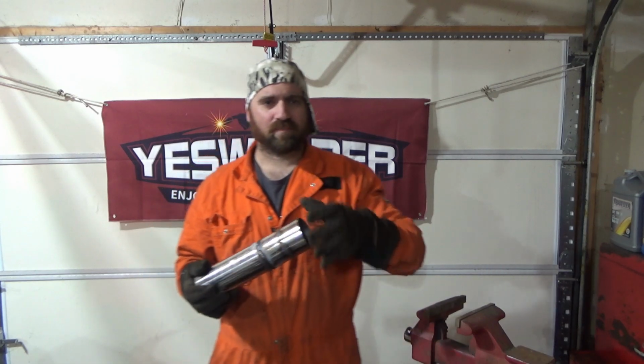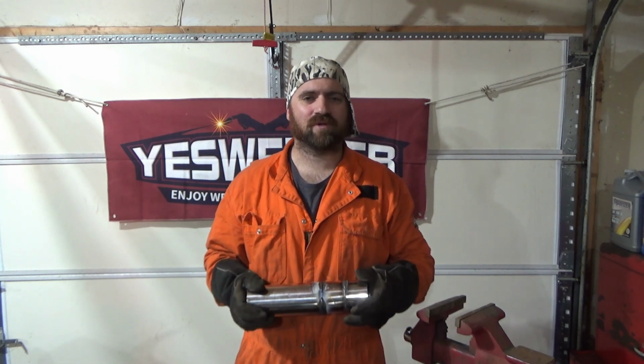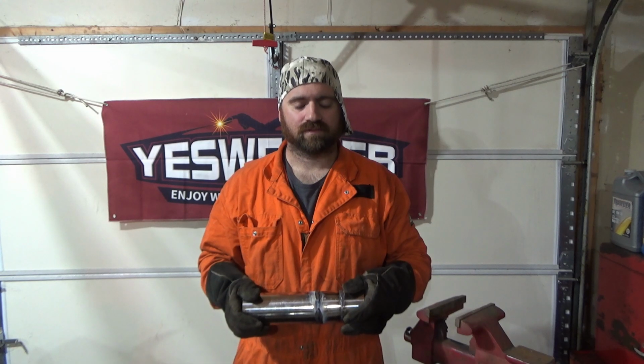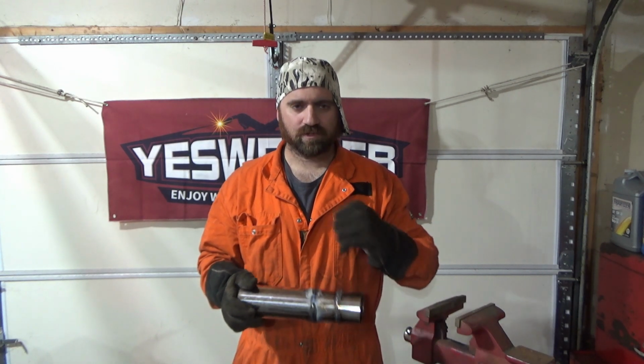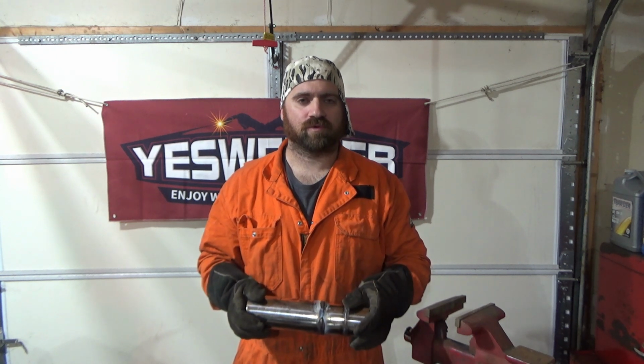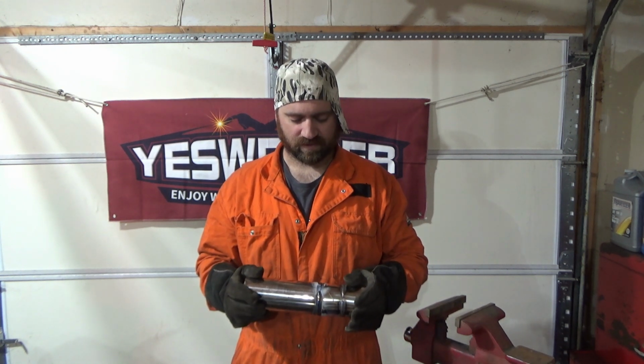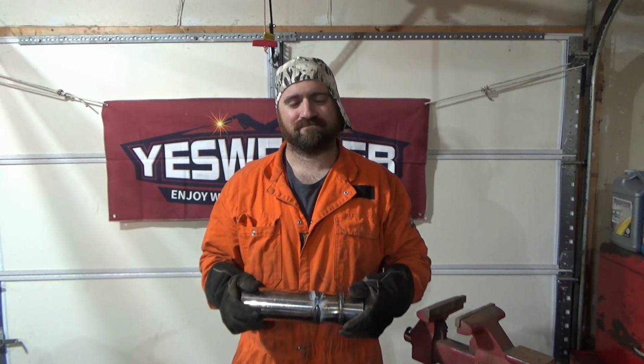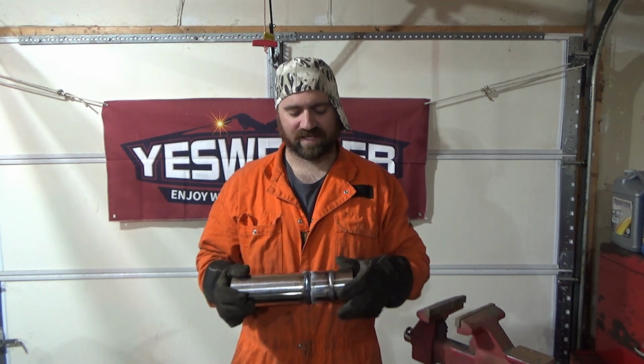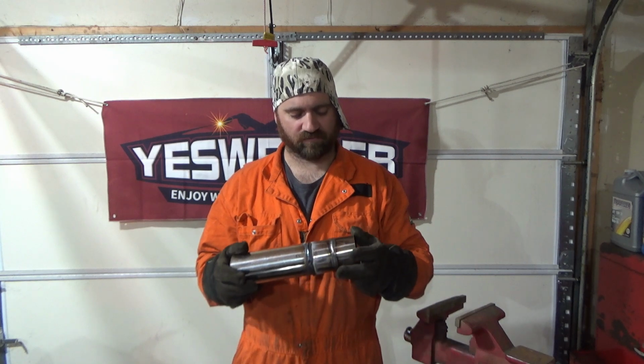So I'm running about 30 to 35 amps, very, very small amount. You have to run pretty quick, and you have to run at an uphill angle because of the way the slag is. And you hear that popping, you hear the tinging after I'm done welding. That's the slag flying off. So it's really important that you wear your safety glasses and all your proper PPE. That way you don't get this stuff in your eye or on your lip. That's the basics of it. That takes a lot of practice to do. It took me a long time before I was able to do that.